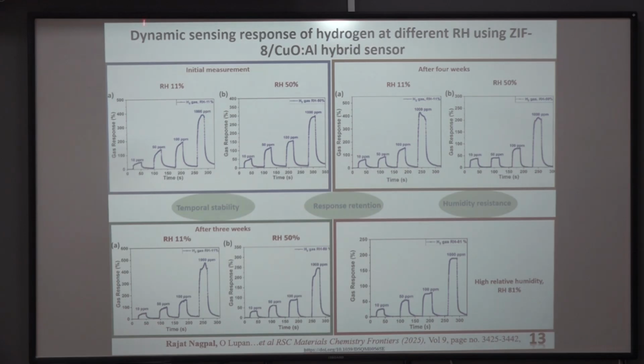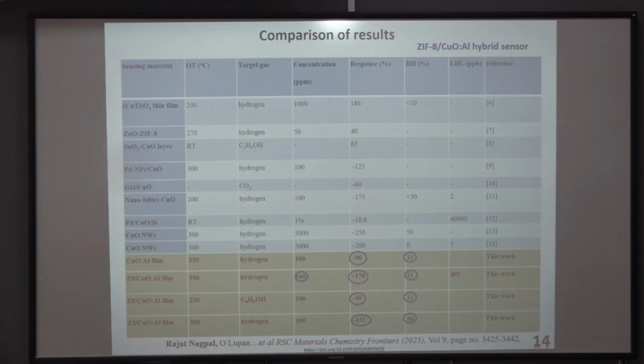Getting more insights from the dynamic sensing curves, further measurements were carried out at different times, going from the initial measurement to after 3 weeks and after 4 weeks. Even after 4 weeks, we can see it retains sensing response for hydrogen at low relative humidity and high relative humidity. It confirms its temporal stability. Even at different relative humidity, going from 11%, 50% to 81%, it shows appreciable sensing response for hydrogen at high relative humidity. It confirms its humidity resistant character.